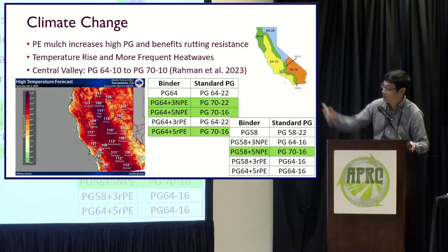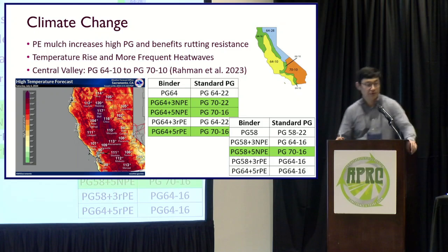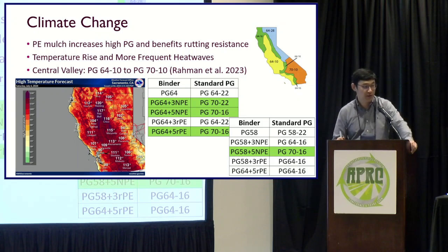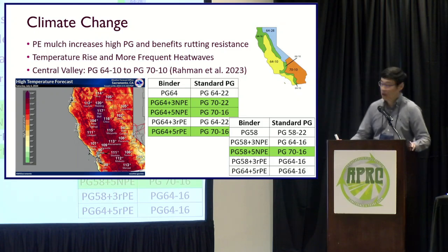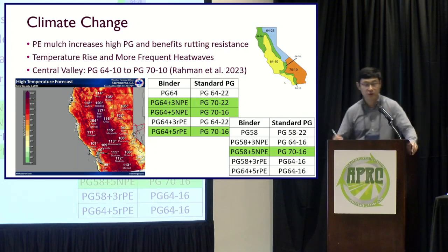With the heat wave over there, like in Chico, we had a few days about 115 and even 120 Fahrenheit this summer. So when we have this high temperature, the rutting becomes the issue. Well, when we use a plastic modified binder, it can help mitigate this problem. Okay? So actually, when we use a plastic, that can help to improve the resilience of the pavement due to